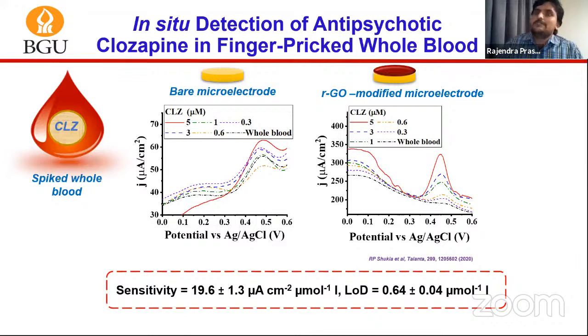Apart from that, we also address one more variability because we use hydrogel carbon nanotube as an electrode material. In that, the hydrogel is a biopolymer which has a net structure, and when you put the solution onto it, the molecules are going to get stuck and may give you some variability. So we're looking for some other material which is much more stable than the hydrogel carbon nanotube. So we explored reduced graphene oxide as a material modification, and we checked its performance also.